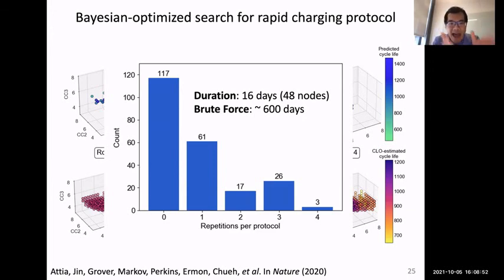So about half of the charging protocols were never explored. That's 117 with zero repetition, meaning we never looked at them. About a quarter of the protocols were examined once, and only three protocols were examined four times. Basically, we repeat experiments when it is necessary and makes sense to do so, and don't repeat experiments unnecessarily. When you employ this all together, you have a 30x reduction in the time it takes to pick out a rapid charging protocol that can deliver the best performance out of the possible 200.